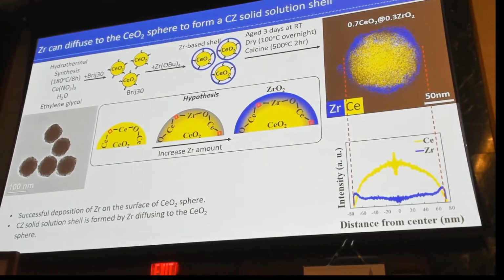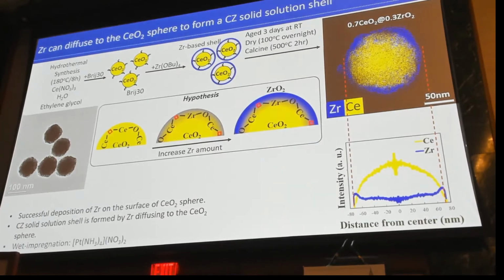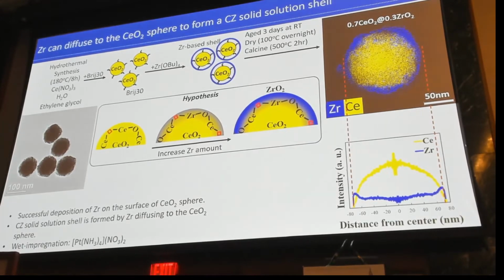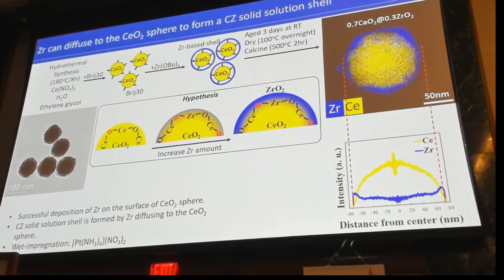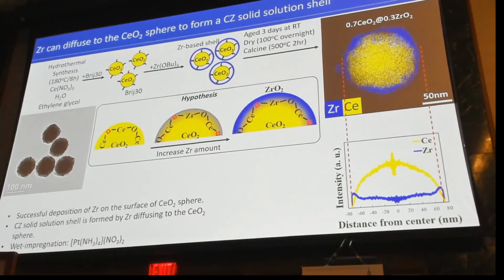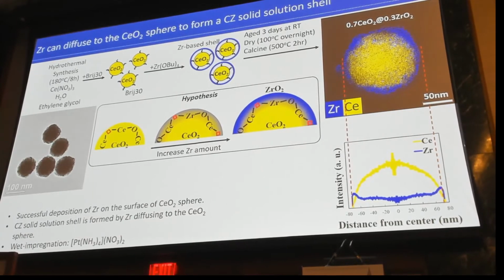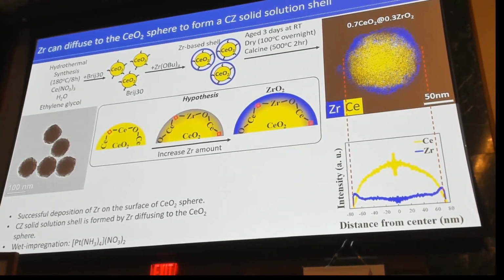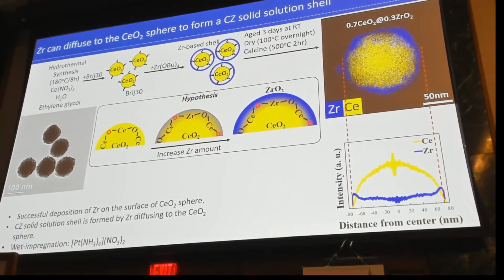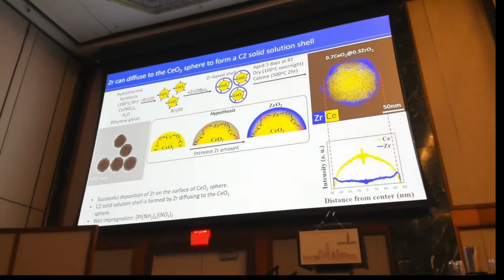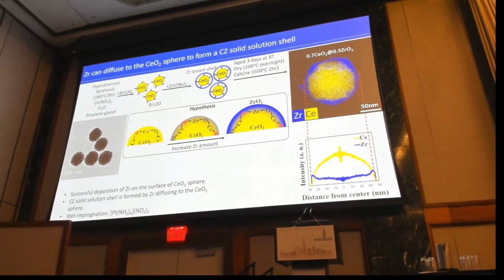So this is our support, and we wanted, of course, to add platinum, because we want to use this material as a three-way catalyst. Here we do wet impregnation, and the loading of platinum is 1.88%. Again, the catalyst is dried at 100 degrees C overnight and calcined at 500 degrees C for 2 hours.